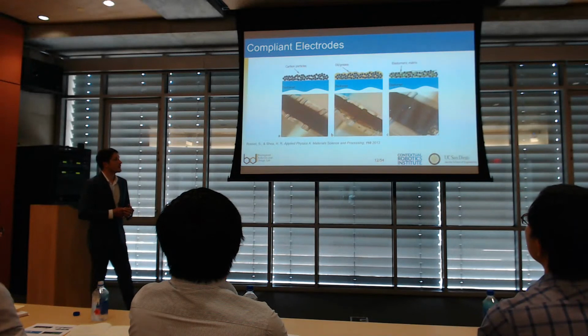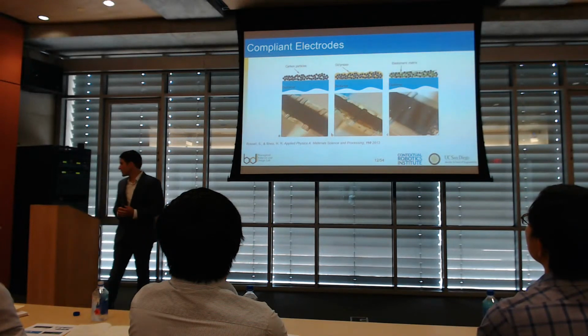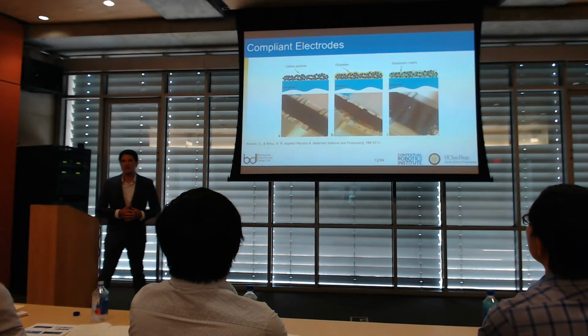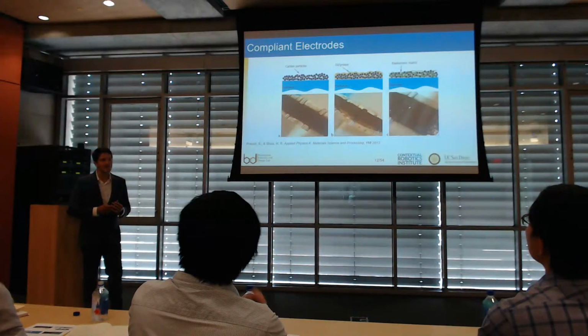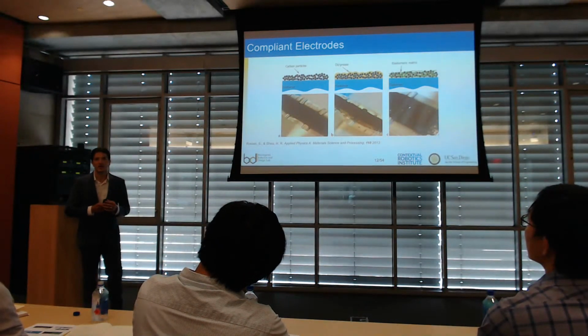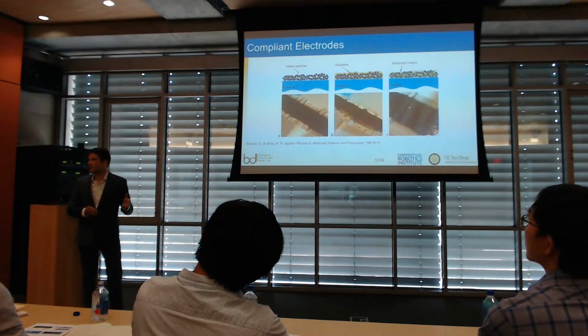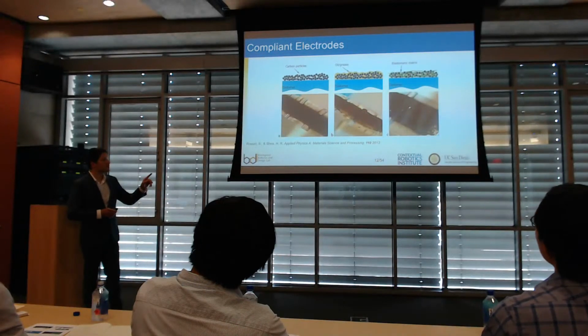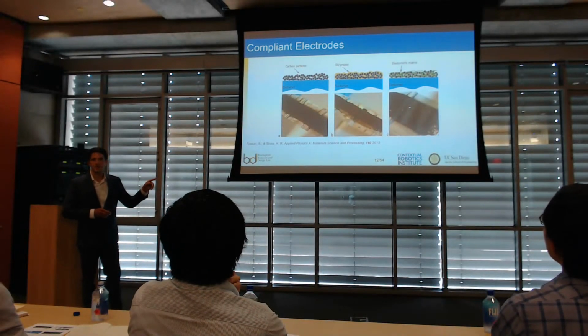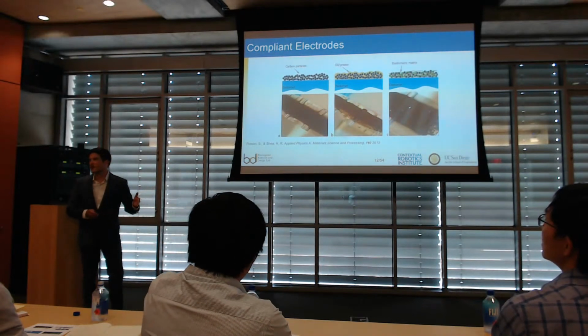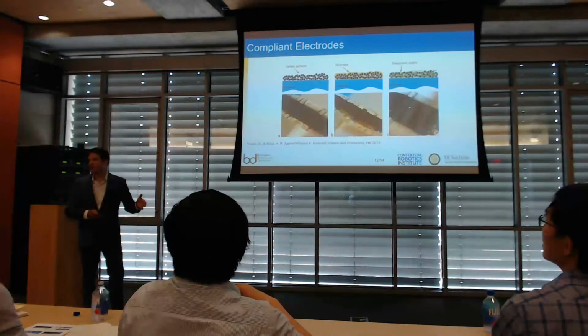But instead of carbon-based electrodes, what we could look at is... another issue with carbon-based electrodes is that if you want to make something that swims underwater, you need to encapsulate it from the surrounding water, or else it will short out to the water. And so what many groups do is, if they use carbon-based electrodes for DEAs, they have to add an additional encapsulating layer on the outside to keep it from shorting out to the water.